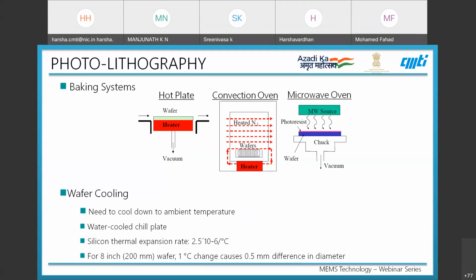That is 2.5 microns per degree rising temperature. So if we are considering an 8-inch wafer, which is about 200 mm in diameter, a 1 degree change causes a 0.5 mm difference in the diameter.